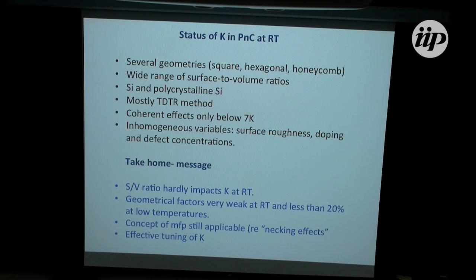About two months ago, the status of understanding, or measurements at least, of thermal conductivity in phononic crystals at room temperature could be summarized as follows. First of all, a range of geometries had been tried. Right? So we had square patterns, hexagonal, honeycombs, etc., various surface-to-volume ratios, silicon, polycrystalline silicon, silicon nitride. The experiments were done mostly with time-domain thermoreflectance (TDTR), and there was an agreement, more or less, that coherent effects were only present at very low temperatures. Well, very low in this community, maybe millikelvin, but a few kelvins and below.